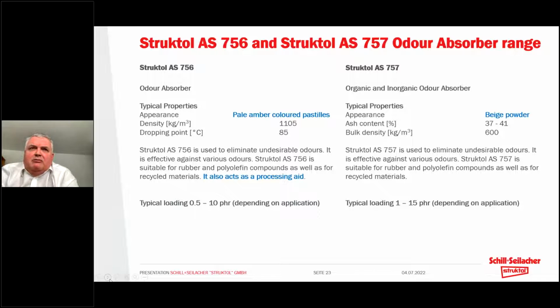I'd just like to share with you an example of a couple of products that were developed early on in our range. We have a pastille product and a powder product. The pastille product is designed with a relatively convenient dropping point, 85 degrees C, so quite ideal to be used in mixing. The carrier system within our pastille product also acts as a processing additive, so the normal lubrication and viscosity reduction could be expected. On the other hand, with the powder product, we have a carrier system based on an inorganic material, a zeolite type product, which offers an additional ability to absorb odors due to the porous nature of that powder. So we have two different approaches with two different chemical and physical combinations of products being available. Next, please.